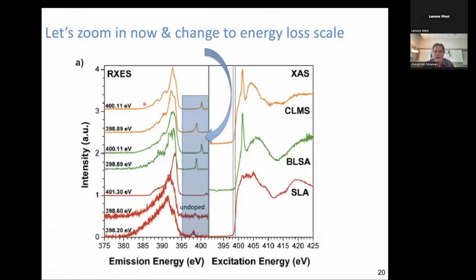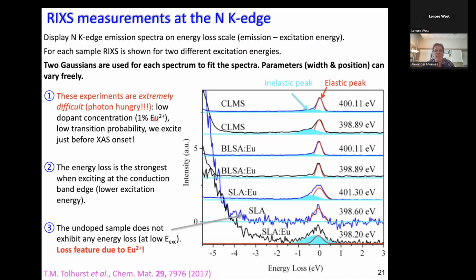If you go back, where do we excite? We excite actually before the absorption even kicks in. So this is basically the least likely way of having photons absorbed. That's the first problem. The next problem is, so it's a very low cross section. The next problem is europium, which we are after, is unfortunately only 1% typically concentration in the dopant. So these are 2 effects that make this extremely photon hungry.